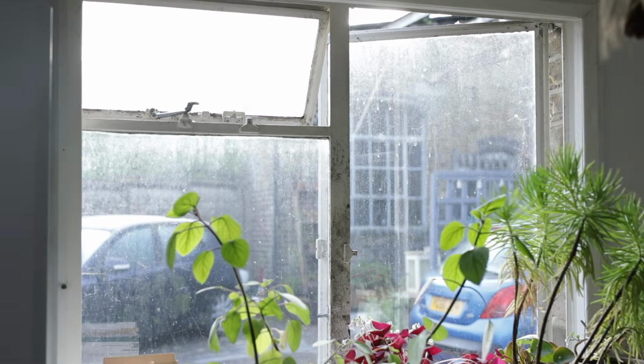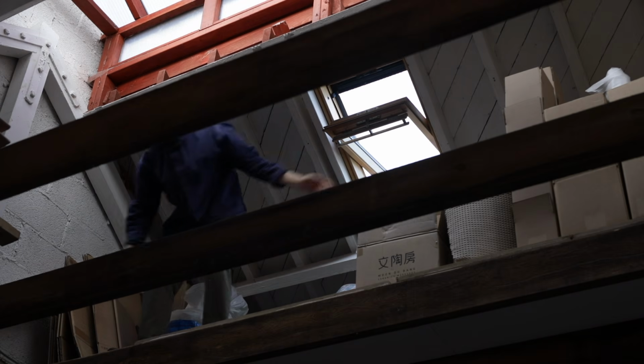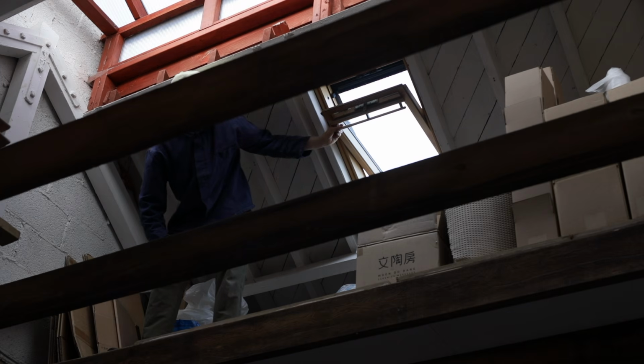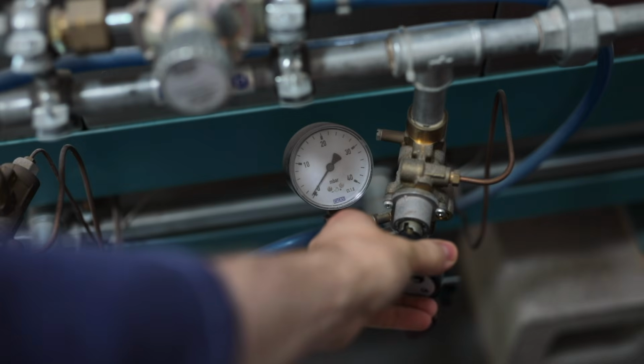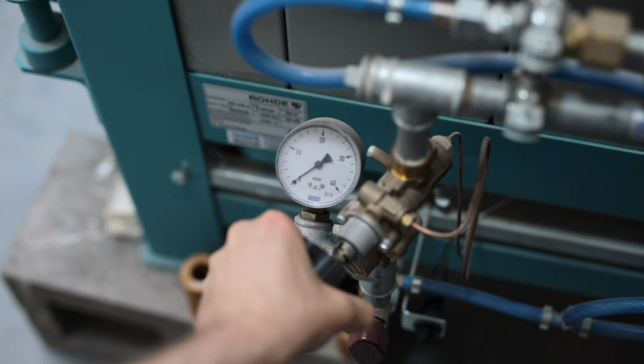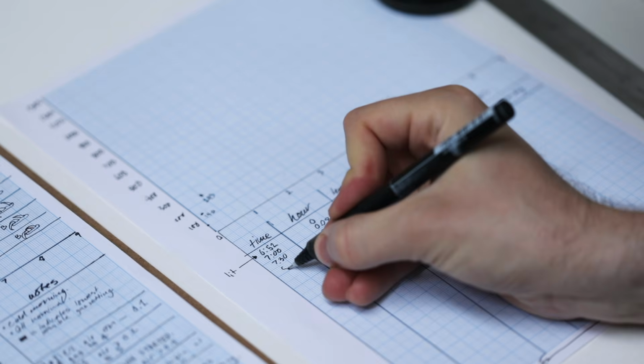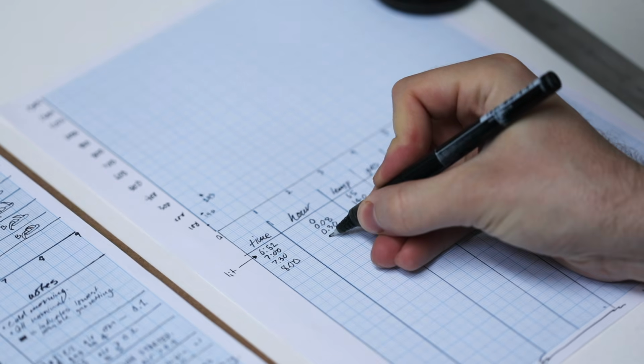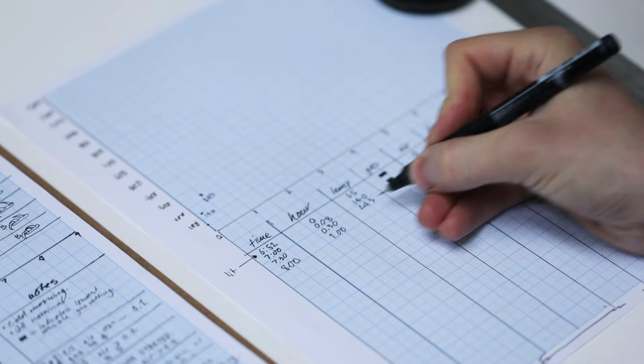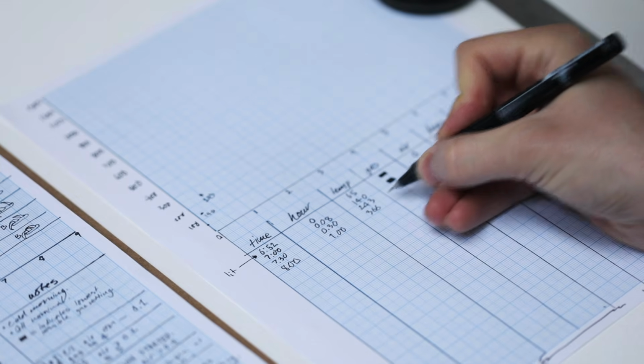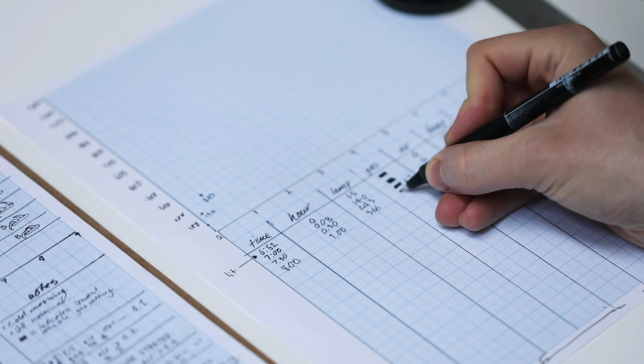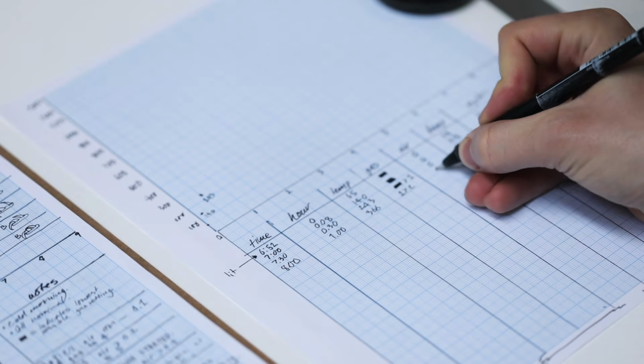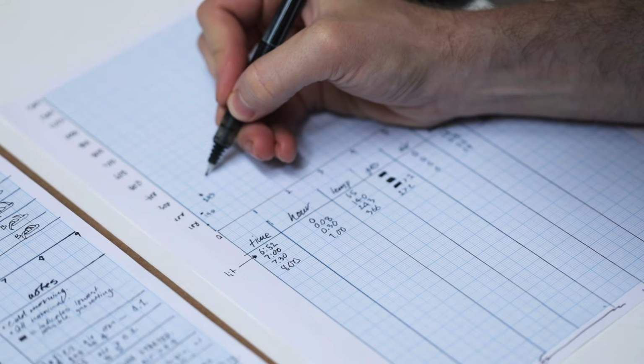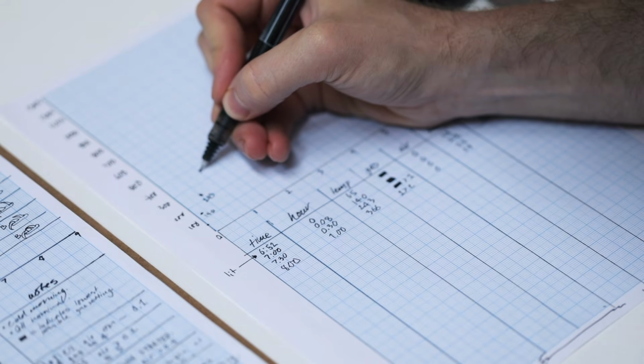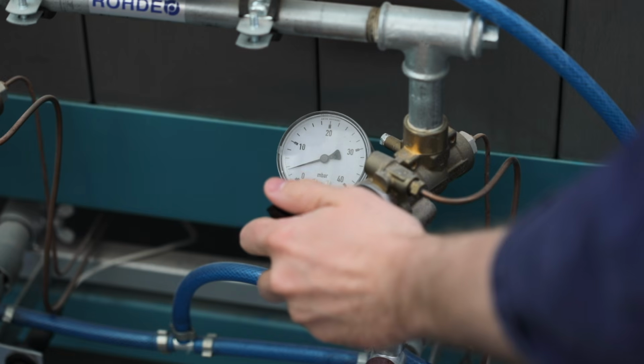This helps to keep the room fully ventilated, and it means fresh oxygen can constantly be drawn in by the kiln as it fires. At the beginning, I let the temperature very slowly climb up, increasing the gas pressure just by a touch every half an hour or so. Additionally, every half hour, I note down the time, the hour, the temperature, the gas pressure, the air pressure, and what position the dampers are at, and then I log the current temperature on the graph above. And with all this information gathered over dozens of firings, it means I can quite easily replicate previous ones, if they were especially successful, for instance.